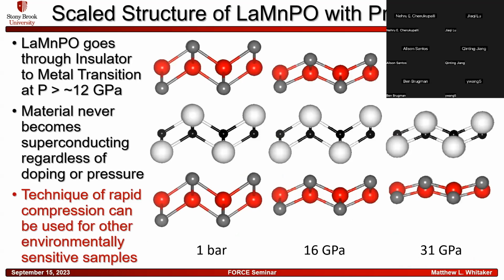So the takeaway from this is that LaMnPO goes through an insulator to metal transition at about 12 GPa. The material never becomes superconducting regardless of the doping or the pressure. But this technique of rapid compression can be used for other environmentally sensitive samples, which is something that we've been doing pretty consistently over the last, wow, I hate to date myself and say 10 years, but it's almost that now.